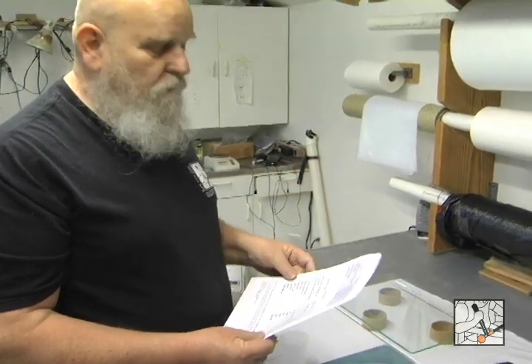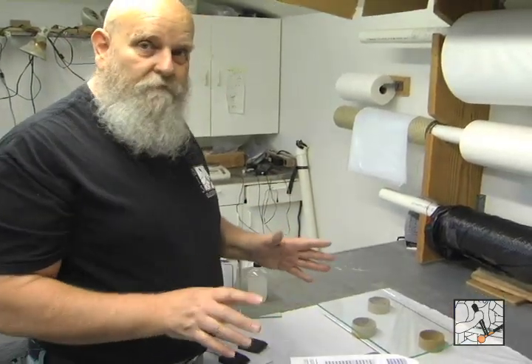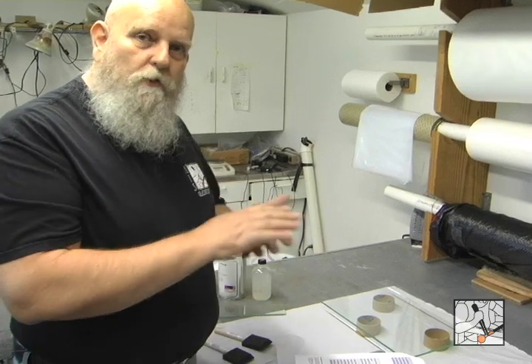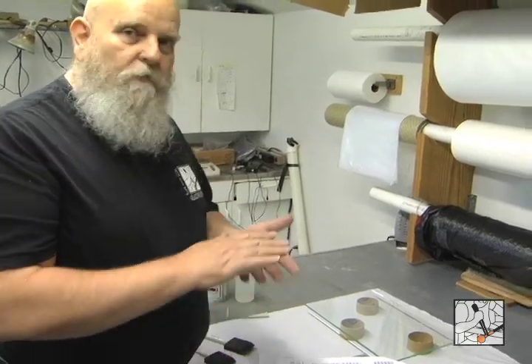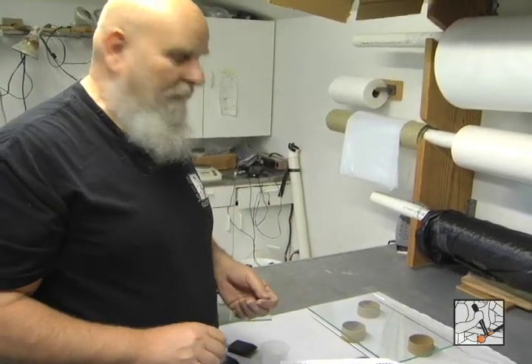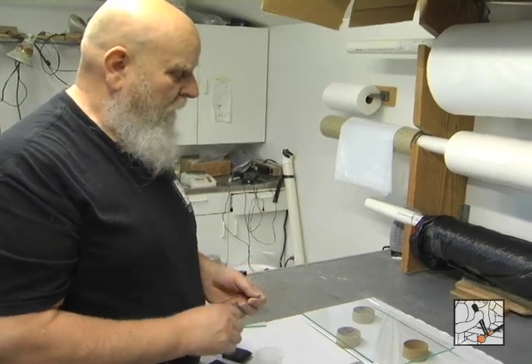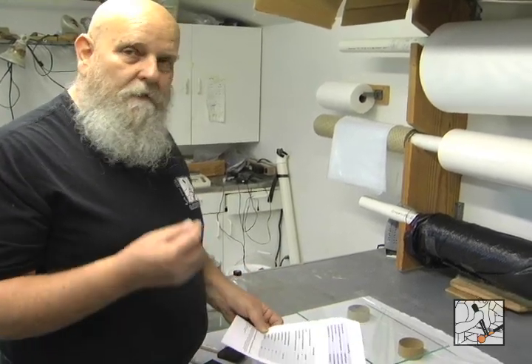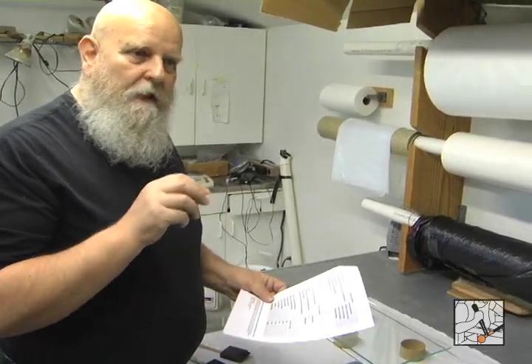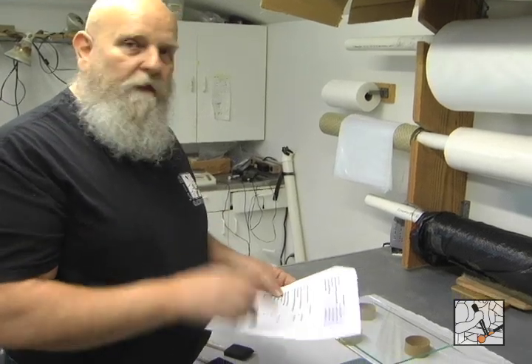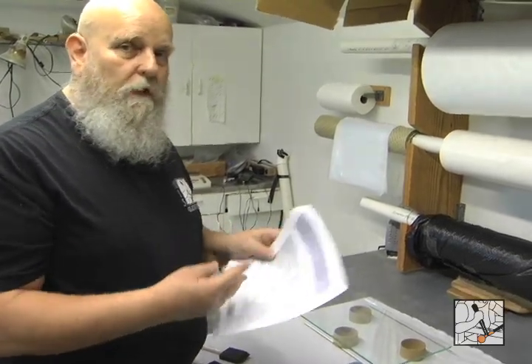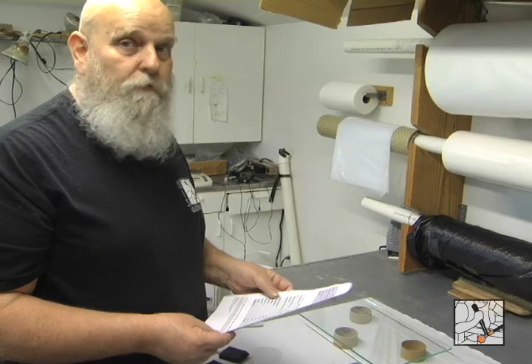After 15 minutes, don't go in because if you start disturbing it, first of all it won't lay flat anymore and it will be very obvious where you tried to repair it, plus the material is starting to cure, and if you disturb it, the molecules aren't going to link up properly and it's not going to get hard.